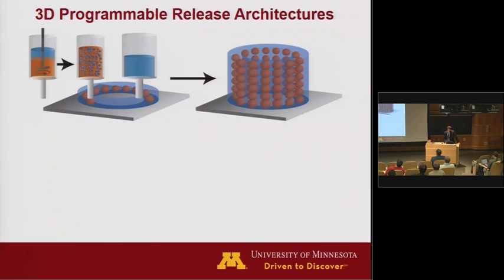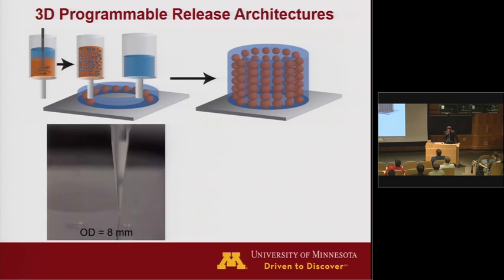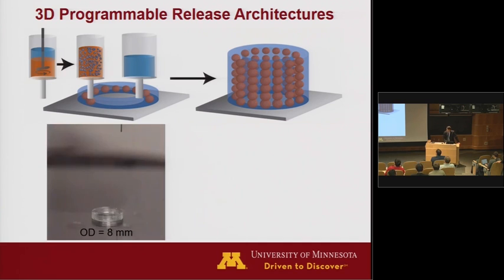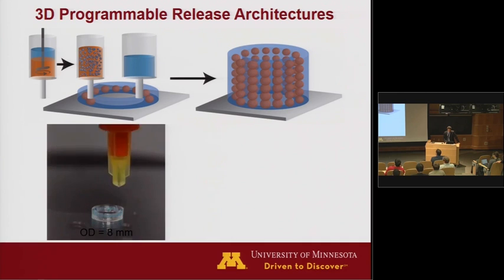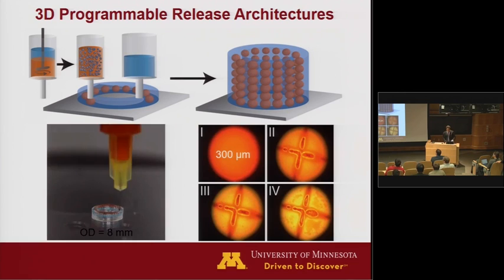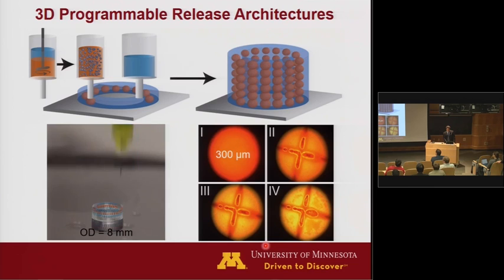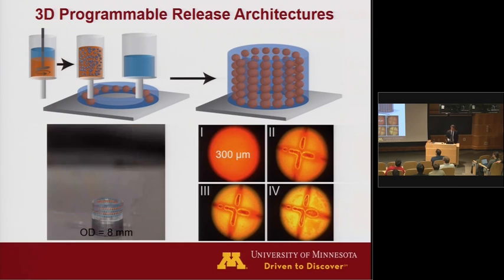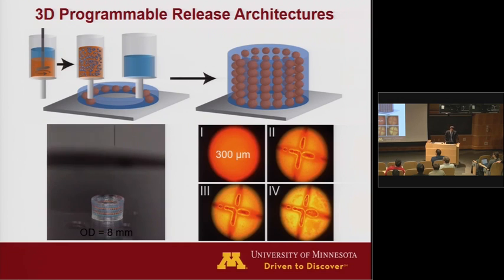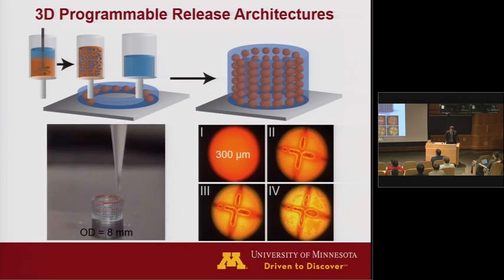Now, this is true not just in 2 dimensions, but also 3 dimensions. So this is a 3-dimensional hydrogel structure that we printed, which we then embedded within these core shell capsules. And so there's blue ones and then red ones. And we can also do this triggered release in a 3-dimensional structure as well. And again, we've actually now 3D printed beating cardiomyocytes that were differentiated from stem cells with release capsules with Brenda Ogle's group at Minnesota. That's not published yet, but it's pretty exciting stuff that we're pursuing.